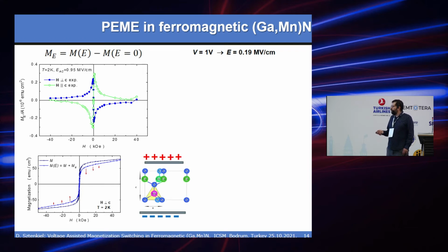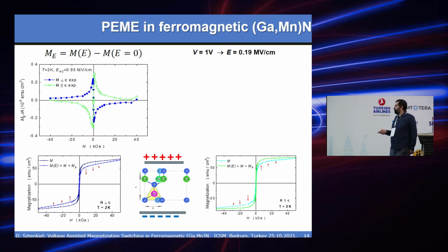So in fact we decrease the magnetization with increasing of the voltage applied to the top of our layer. So the magnetoelectric signal is negative and in antiphase with the applied AC voltage. The situation is opposite for the hard magnetization direction, as shown here. Now we increase the magnetization with application of positive voltage to the top of our layer, so the signal is positive for positive magnetic field and in phase with applied AC modulation.